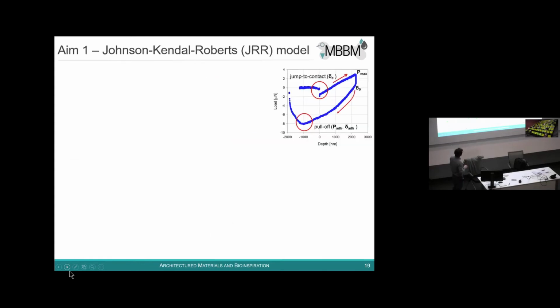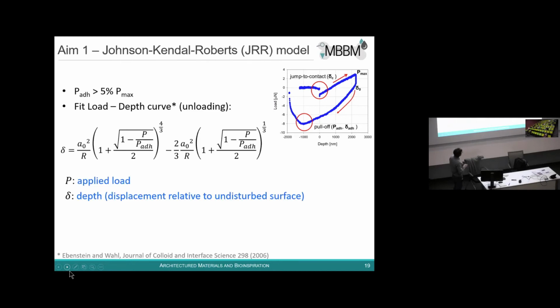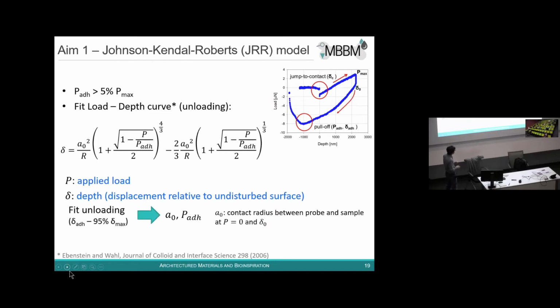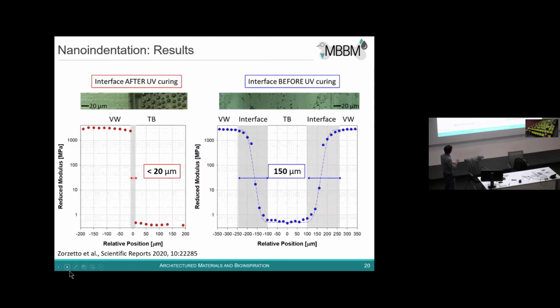So yes, we needed to develop the indentation a little bit. Fortunately, there is already quite some literature on indentation of very soft materials, so we could exploit this, and basically from our measurement we could estimate the contact radius between the probe and the sample and use this to derive the so-called reduced modulus of the indentation. And now I jump to the results.